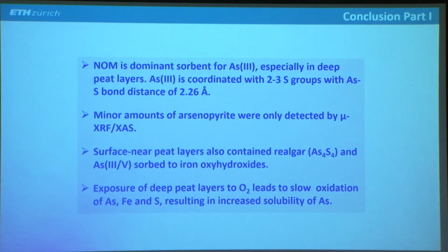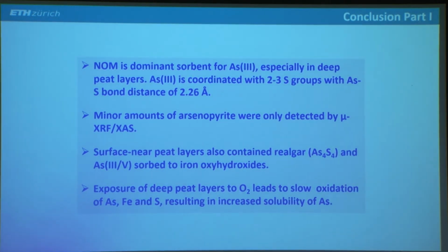Also, some minor amounts of arsenopyrite were detected in the deep peat layers, and the surface near peat layers, which I didn't talk so much about, contained mainly realgar and also some arsenic-3 and arsenic-5 sorbed through iron oxides, and also a little bit of this NOM type binding to sulfur. And the experiment showed that exposure of these deep peat layers to oxygen actually results in a mobilization of arsenic. So it's actually a very different behavior than you would expect from a mineral aquifer, where oxidation would result in an immobilization of arsenic, and a reduction would result in a mobilization.